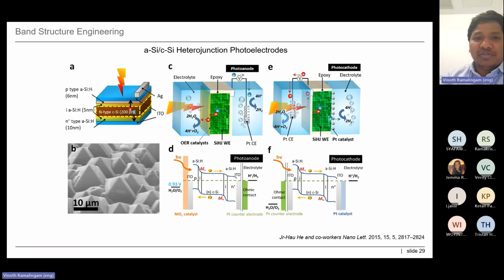Again, this is one of our group's previous works at KAUST, where they developed an amorphous and crystalline silicon based heterojunction photoelectrode. When they form this kind of heterojunction, it's very interesting to see that these photoelectrodes can be used as a photoanode and a photocathode by simply changing the catalyst. When they put the oxygen evolution catalyst on the front side of the photoelectrode, it works as a photoanode, whereas when they coat platinum as a water reduction catalyst on the rear side, it works as a photocathode. So with this unique structure, you can tune the same photoelectrode as a photoanode or photocathode by simply switching the catalyst, either front side or back side, so it can be used as a dual photoelectrode for two different applications.